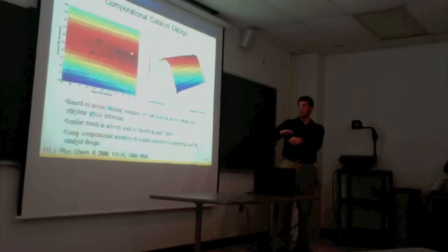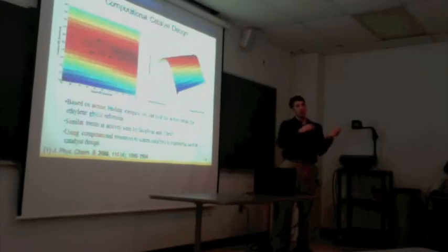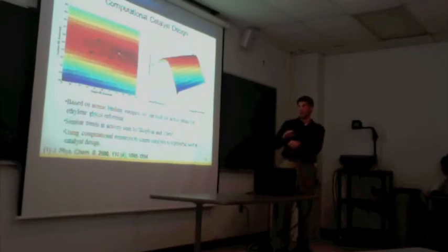Now this other one, which is the most active one we found, this nickel platinum platinum, is essentially platinum, and then we deposit nickel onto the surface of platinum. We do this in an ultra-high vacuum chamber, which means it's very low pressure. There's a platinum surface, and we sputter nickel onto it at a certain temperature, and it will spread out onto the surface, and we can create this catalyst that we want. So it's nickel on top of platinum.